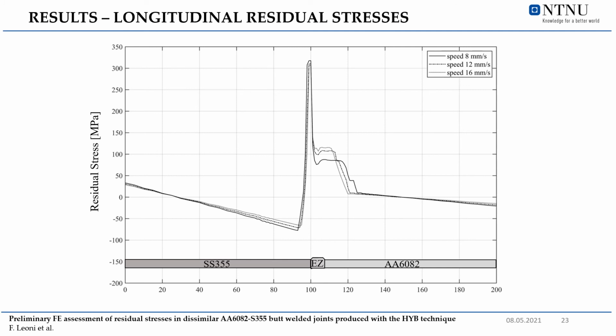Here, a difference between the 3 cases can be observed. In particular, it can be noticed how the welding speed affects the width and the amplitude of the stresses. It is noticed that increasing the welding speed brings a narrower plasticized zone with a higher stress magnitude.